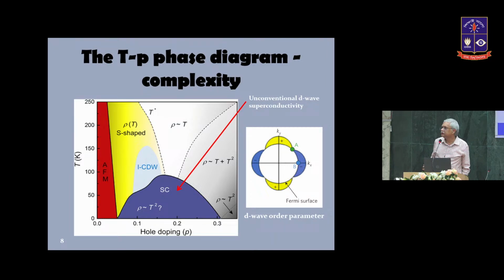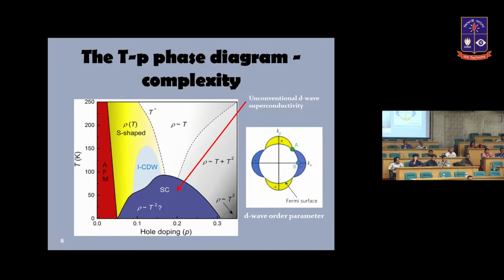In addition to superconductivity, you have incommensurate charge density wave. There is an anomalous normal state, which does not conform with Fermi liquid, where you have the resistivity going linearly with temperature. And you also have spin density wave in this region. And when you go to the overdoped side, by overdoped I mean you get to the hole doping where the maximum of superconductivity has been exceeded, it becomes kind of Fermi liquid-like, but it has some properties which are not exactly like Fermi liquids. So this is a very serious challenge, because I think you know that the standard model for condensed matter physics is the Fermi liquid theory.